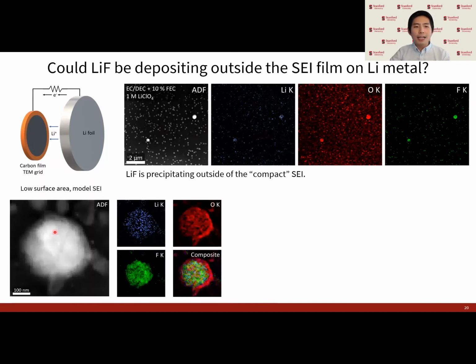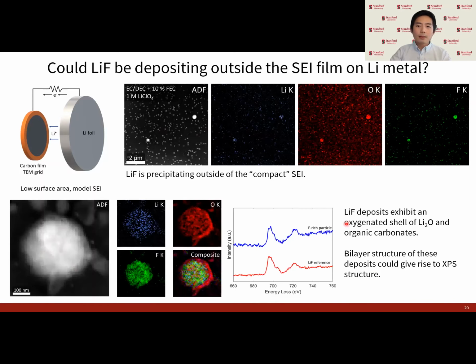And looking closer at the actual nanostructure of these SEI particles, we can see that they have a heavily fluorinated core along with a more oxygenated shell, creating this sort of core-shell morphology. From the fluorine spectra, we can see that the core is lithium fluoride, with this outer shell consisting of lithium oxides and organic carbonates. And these bilayer structures could be what's giving rise to this sort of outer organic, inner inorganic SEI structure from XPS.